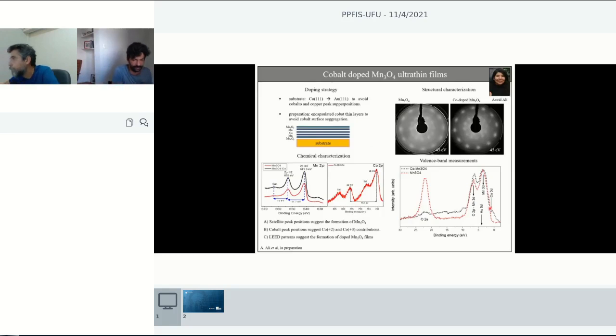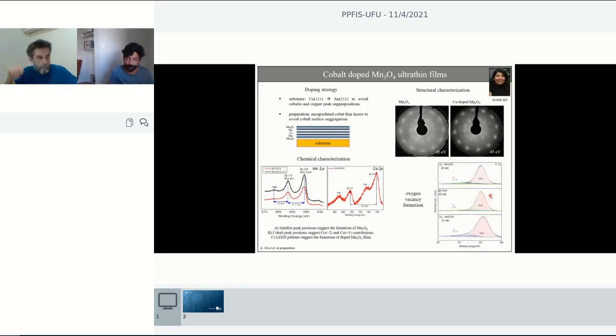What's nice about this is when you're doping something, you don't want to make a mixed oxide. You don't want to prepare, let's say, a quaternary oxide. So you want to have a small amount of a dopant that changes the electronic properties, preserving some of the structural properties of your host material. That's the Mn3O4, and when we see that this is structurally pretty much the same, and we just see a difference because of the electronic contribution that appears because of the cobalt, we have a lot of evidence that we are actually doping and not forming another type of oxide.